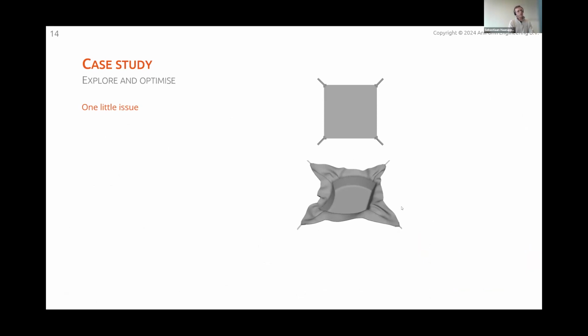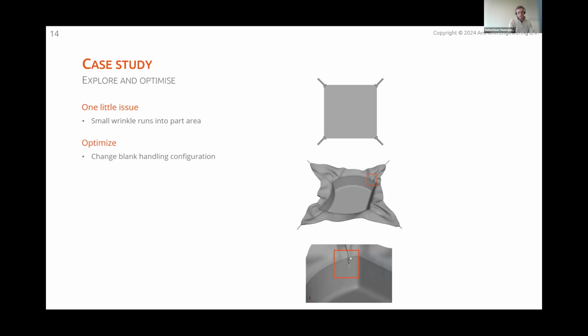There's one little issue. So this is the situation. Laminate tensioned like this, and then this is the resulting deformation. There's a little wrinkle that runs into the part area over there. We can zoom in. And well, what can we do about that? Again, we have a simulation tool, so we can do anything we want. So one thing was just to change the blank handling configuration. And by that, I mean to change the orientation and position of the springs attached to the laminate. So instead of 4 springs pulling diagonally on the laminate, we now put 2 springs per corner and pull perpendicular or in line with the fiber direction.